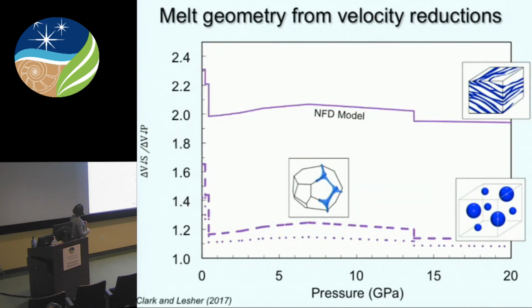So here we have this ratio of melt velocity as a function of pressure. We're going to start with the network flexibility model. And so here we have our three geometries, right? Isolated melt pockets, sheets, and equilibrium melt texture. And what you can see, again, perhaps not surprisingly, is that we have a very weak pressure dependence for this ratio as a function of pressure.